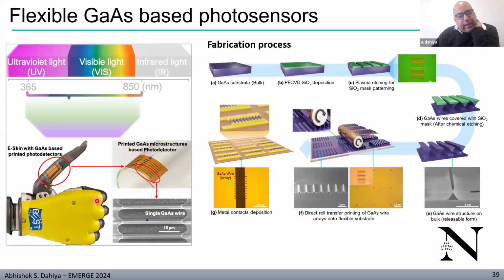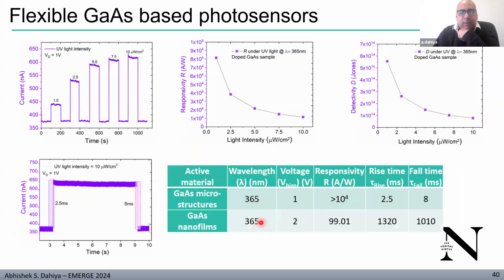Coming to another example, we have fabricated some high-speed gallium arsenide-based photodetectors using direct roll printing onto flexible substrates. The advantage of these gallium arsenide-based devices is that they are wide-range photodetectors. They respond from UV to infrared light. In this case, the gallium arsenide is fabricated from bulk wafers, not from SOI wafers like the silicon case. This is the shape of the fabricated ribbons, and this is how they look after transfer printing. Then we deposit our source and drain metal for these gallium arsenide wires.